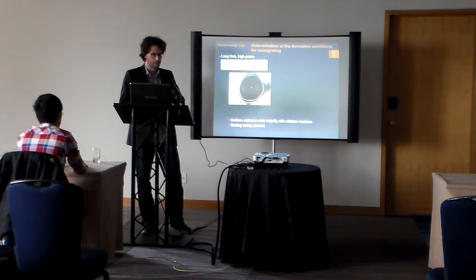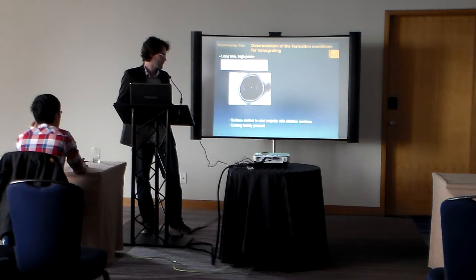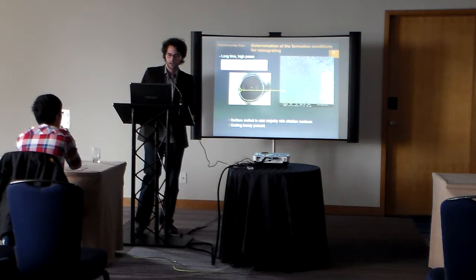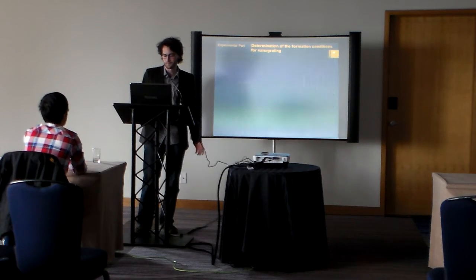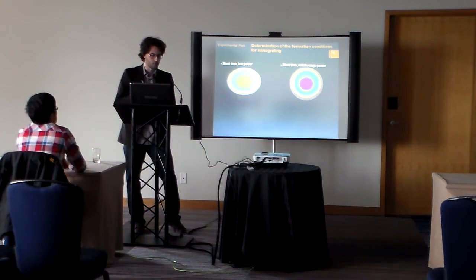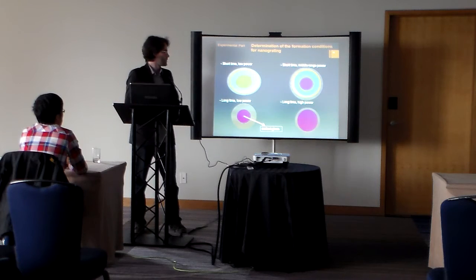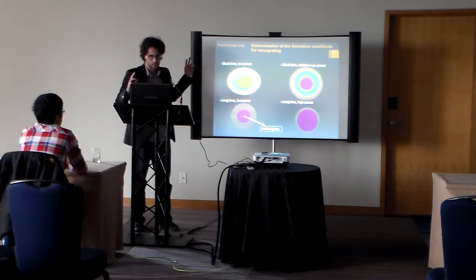With high power, there's only a big melted spot with a lot of ablation residues, as you can see here, and there's no significant region of grating. So as a summary for the different conditions, you can see here the ideal parameters.